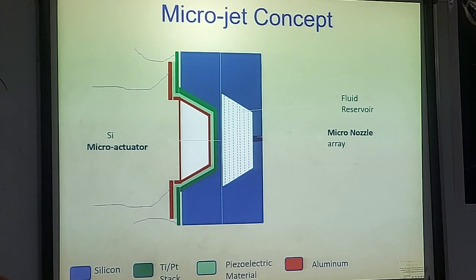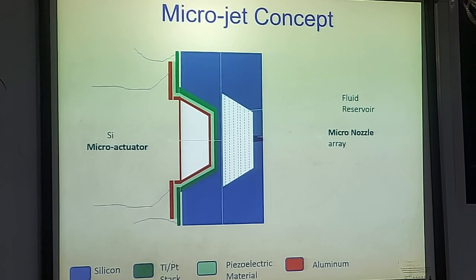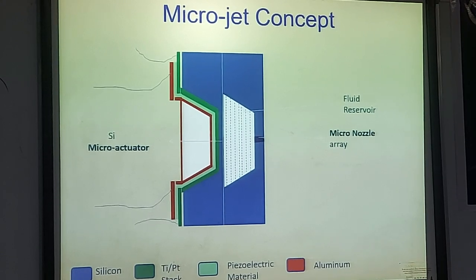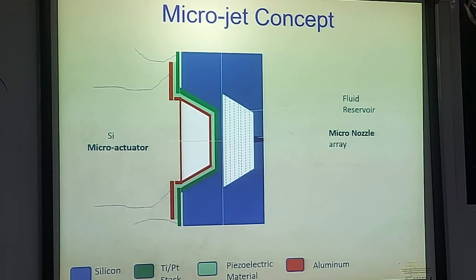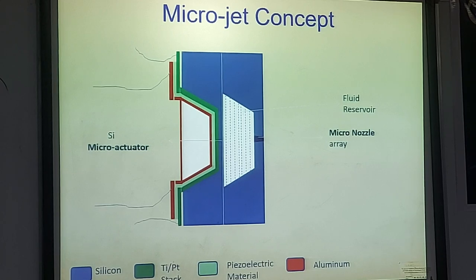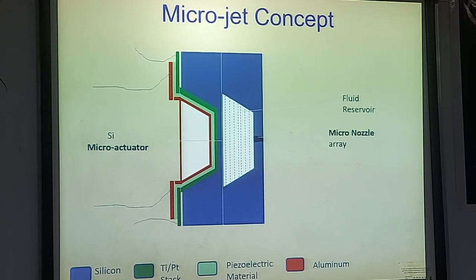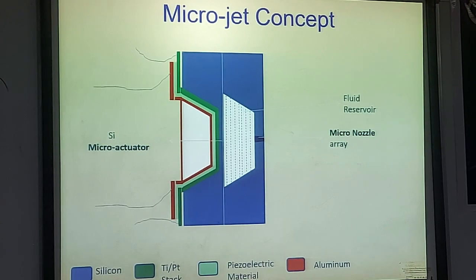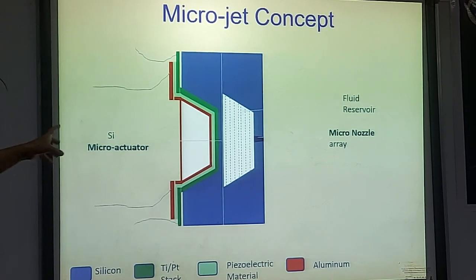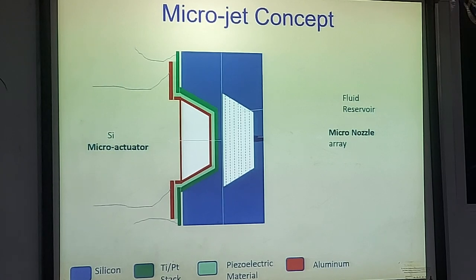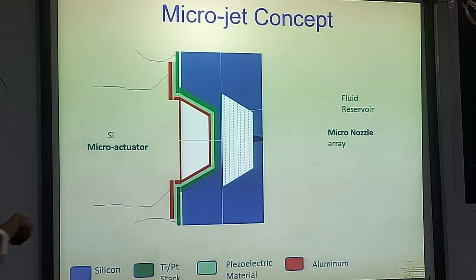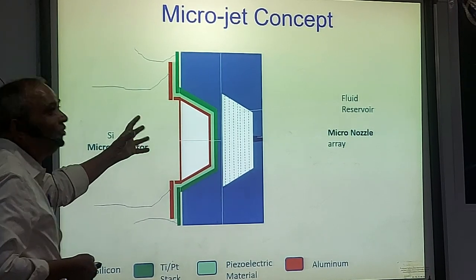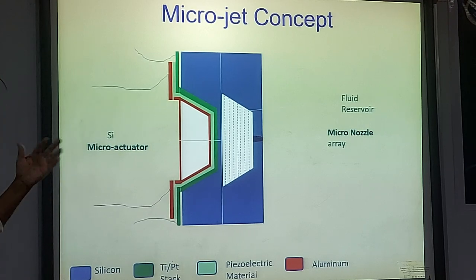Here, the piezoelectric thin film, the piezoelectric material that we deposited, is used not as a sensor but as an actuator. In the beginning, I mentioned that we need both sensors and actuators. When you apply an electrical potential to the piezoelectric material, it deforms. This deformation makes the thin silicon diaphragm undergo some compression.